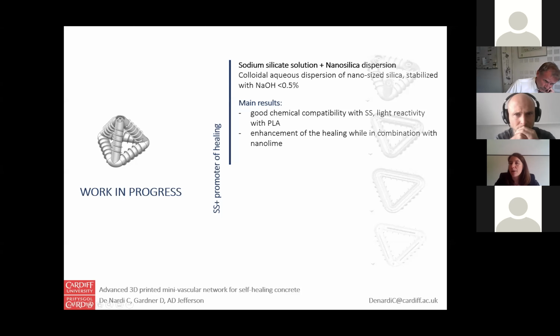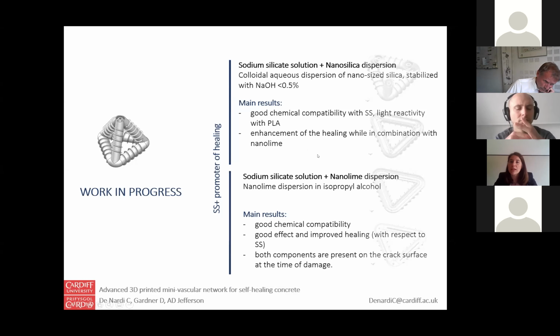So again, we have a problem of reactivity of the oxidized group of the PLA with everything we put inside. But we still have a positive value when we consider the combination of the nanolime. So we have the sodium silicate, the nanolime, and the nanosilica as well. When we use a nanolime dispersion and the sodium silicate, we have an excellent compatibility. So we are giving the system more calcium hydroxide, and we are working on the carbonation. We have a good compatibility, and we have a really good effect in terms of healing. The difference between this second trial and the first one is around 10%. So I think it will be promising.